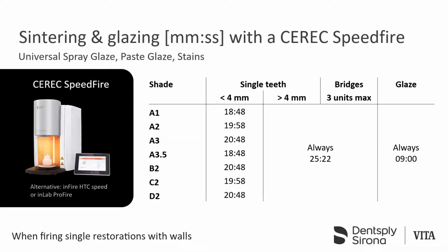When firing single restorations with walls less than 4 mm thick, the sintering times may vary between 18 and 21 minutes depending on the tooth shade. By the way, restorations with the same shade may be sintered together. In general, glaze should be fired for 9 minutes.